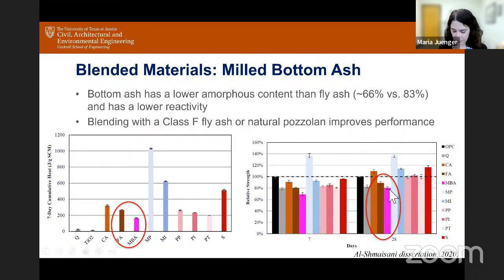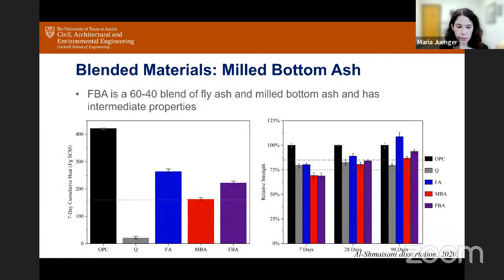We need something better. And so what you can do, for example, is blend it. In this particular R3 test, this is the cumulative heat of the fly ash. This is the milled bottom ash in red, and this is a blend of 60% fly ash, 40% milled bottom ash. That blended material suffices in terms of performance. It suffices in terms of strength. And so you get a better material by optimizing your resources through blending.